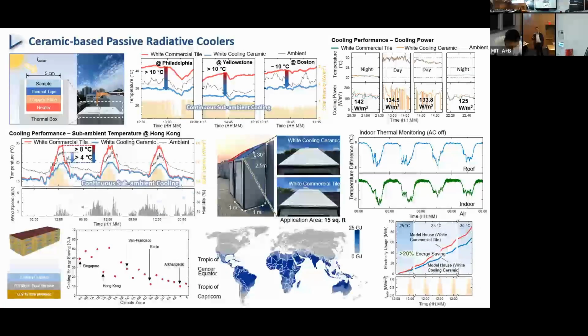We conducted a few tests in Hong Kong first, and we continuously monitored the ambient cooling. The ceramic tile temperature itself is around 4 degrees Celsius lower than ambient temperature. Compared to the commercial white tiles, we can achieve about 8 degrees Celsius lower. We also measured the cooling power, and with almost ideal solar reflectivity of 100%, we achieved a cooling power of 134, about 140 watts per square meter, almost reaching the theoretical limit.